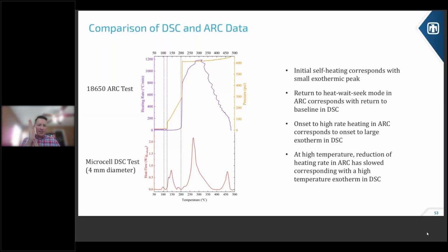The first dashed line corresponds with self-heating in the full 18650 and the small exotherm in the DSC. The second dashed line corresponds with the second self-heating and the medium-sized exotherm in DSC. And then the next dashed line at 200 degrees C corresponds with the onset to thermal runaway, which also is the onset to this largest exotherm. So now we have a direct corollary between a very large exotherm at a very small scale and an actual thermal runaway in a real 18650 battery.